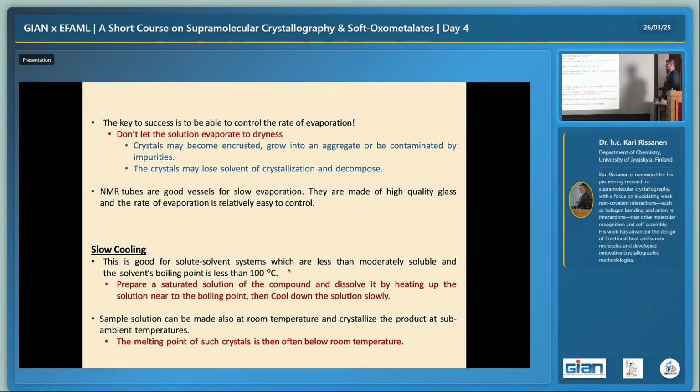And that's the idea. So the point in there is that you can also do it in a different way, that you start from the room temperature and you put it in the deep freeze. So you go from 25 to -20, and then the crystals grow when you go, let's say, to -10. But now there is a difficulty with this, because if you now take that tube where you crystallize the vessel to the room temperature, it will dissolve back.